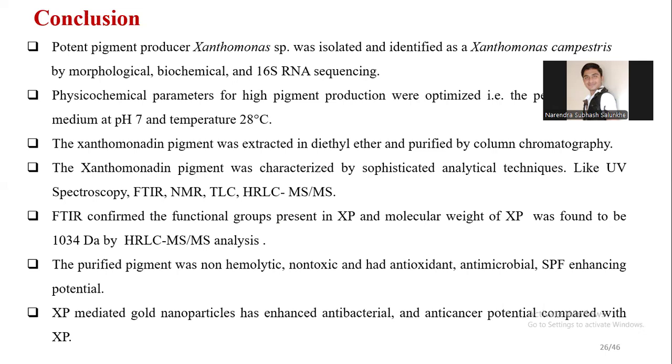Then the pigment was characterized by visible spectrophotometer, FTIR, HRLCMS, NMR, and TLC. Then the purified pigment was non-hemolytic, non-toxic, and had antioxidant, antimicrobial, and SPF enhancing potential. Then the XP-mediated gold nanomaterial has enhanced antibacterial activity and anti-cancer potential as compared with xanthomonadin.